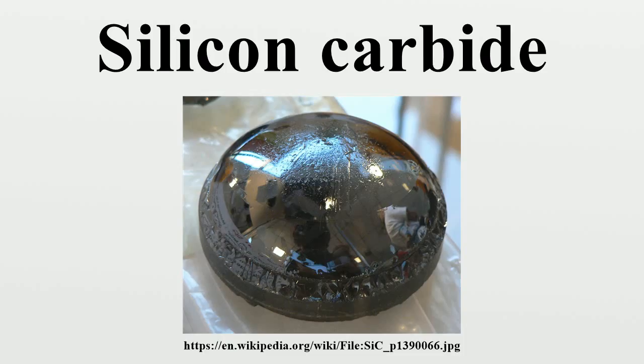A modified Lely process involving induction heating in graphite crucibles yields even larger single crystals of 4 inches in diameter, having a section 81 times larger compared to the conventional Lely process. Cubic SiC is usually grown by the more expensive process of chemical vapor deposition. Homoepitaxial and heteroepitaxial SiC layers can be grown employing both gas and liquid phase approaches.